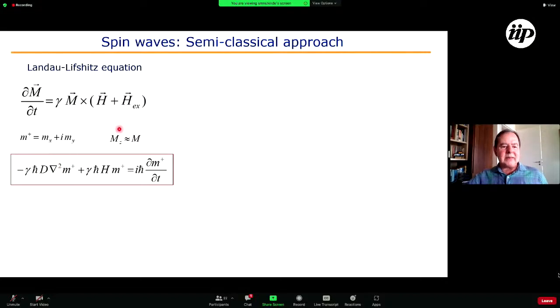Laplacian of m, the Laplacian comes from the exchange interaction that gives coupling between the spins, and when there is an angle between the spins, the derivative comes in, plus gamma h, the magnetic field, m, equals i h bar dm/dt. See that the equation for the magnetization has precisely the same form as the Schrödinger equation for a particle. This is interesting and has important consequences.